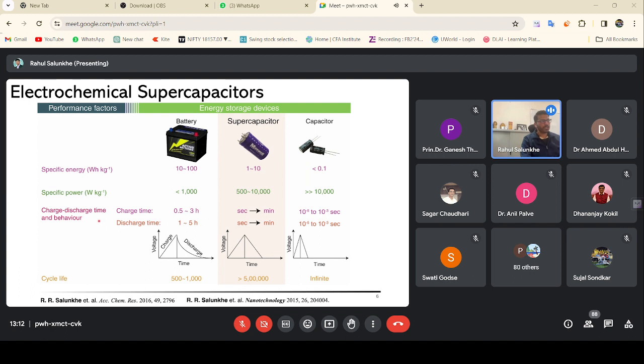If we consider the charge discharge profile, firstly, in case of a battery, the battery gets charged very linearly, but the discharge is not linear. It is a certain exponential decay. Whereas in case of a supercapacitor and a capacitor, we can get a very linear charge and very linear discharge. In a supercapacitor, the charging and discharging time varies from a few seconds to a few minutes, whereas in a capacitor it varies from 10 raised to minus 6 second to 10 raised to minus 3 second, very few seconds, quickly charged and quickly discharged. In case of batteries, charging takes half an hour to 3 hours, whereas discharge time is from 1 to 5 hours because it is a very slow discharge.